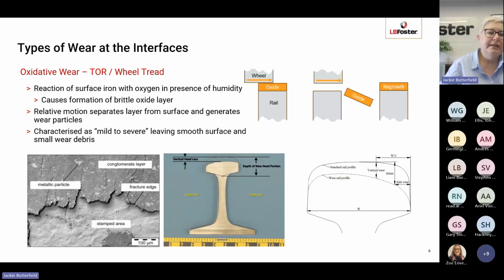So under a scanning electron microscope, this is what the surface looks like. So the darker grey is the oxide layer and the lighter grey is the underlying steel below it. So this layer flakes off and forms wear debris and particles, which then end up in the third body layer or end up in the track bed and the ballast. So this type of wear is often characterized as being mild to severe, depending on the environmental conditions, and tends to leave a smoother surface than the adhesive wear, and much smaller wear debris particles.